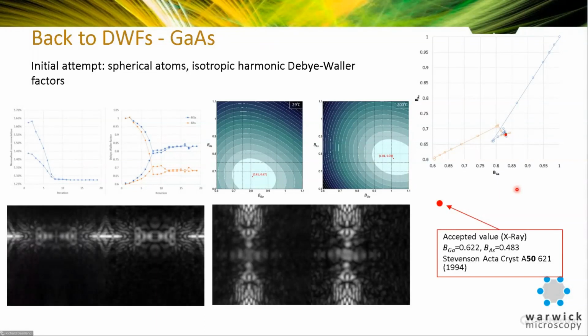And what's the reason? Well, I think this is down to the independent atom model, actually, and I think what we're seeing here are indeed bonding effects. So if you look at my best fit simulations here, experiment on this side, simulation on this side. You can see, okay, plenty of this is a good fit, but there are certainly bits here which do not fit very well. And the only thing I've got left to change here is a charge on the atoms. So that bonding between the atoms is presumably the origin of this difference here.